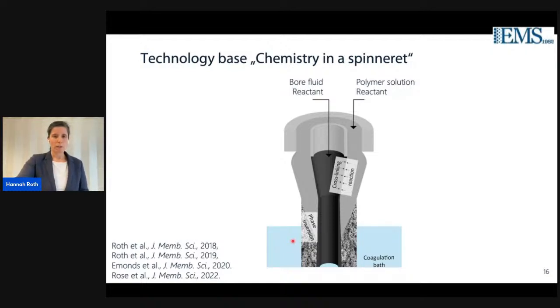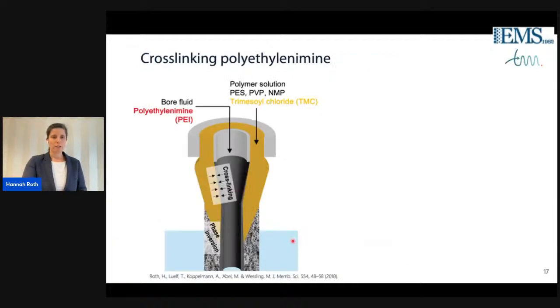And I want to show here now the earliest publications on this, where I showed how polyethylene imine can be cross-linked from the bore fluid, as it is water soluble, and then combined with TMC from the polymer solution, which is a typical cross-linker, also known for reverse osmosis membranes.